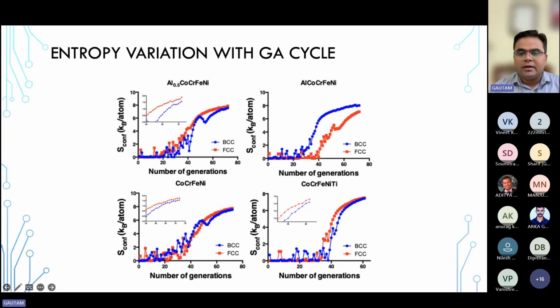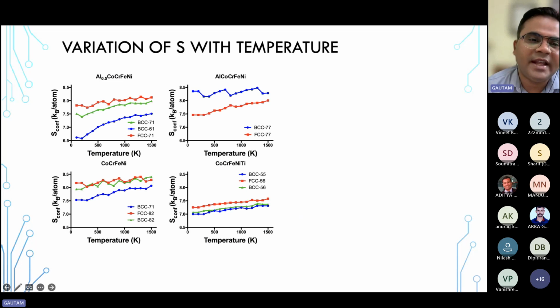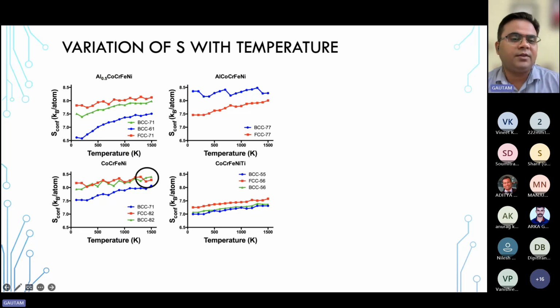Similarly, for titanium, we found that FCC seemed to have the greater entropy parameter. So it can basically predict the room temperature phase stability. So we varied the temperatures, and as we vary the temperature, you just look at FCC versus BCC. As you can see, the green and the red part, FCC is basically a stable phase throughout the temperature and shows an increasing trend. Cobalt, chromium, nickel at room temperature, FCC is stable, but as we go to higher temperature, it flips. So it starts to give us a prediction that BCC can get stable at high temperatures.